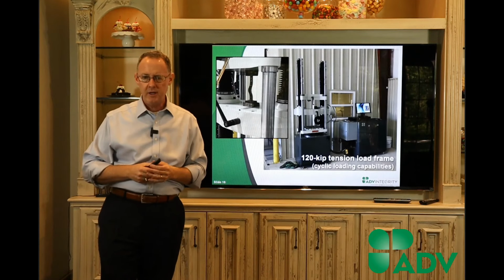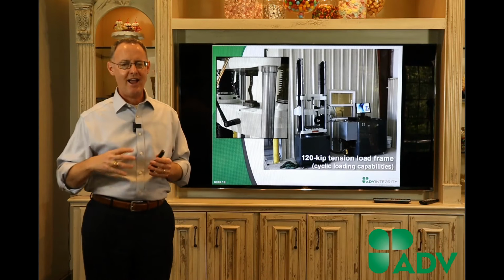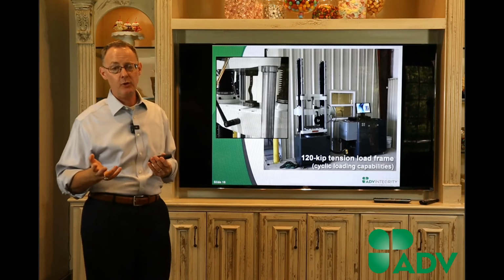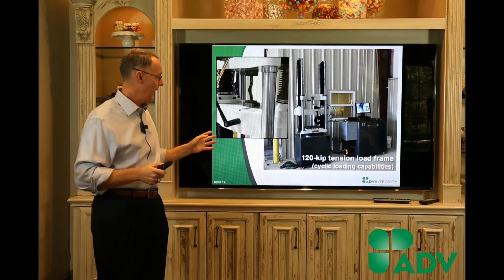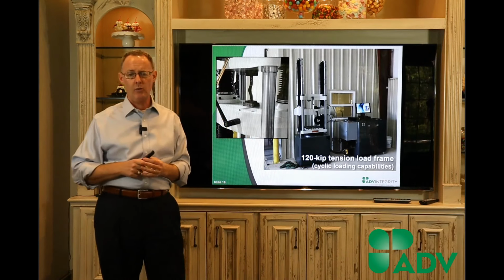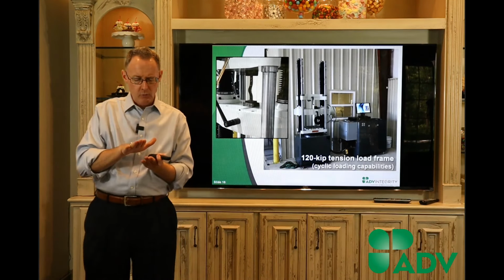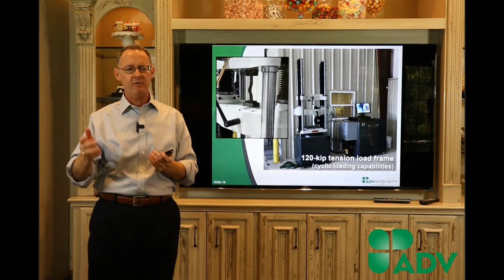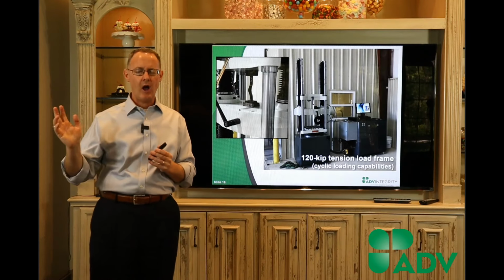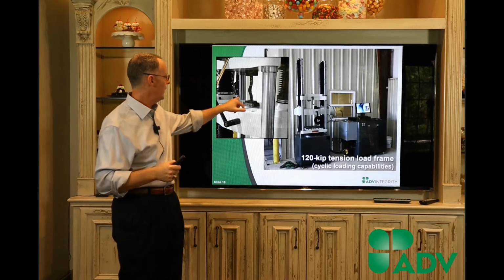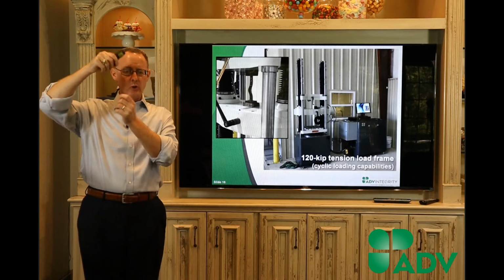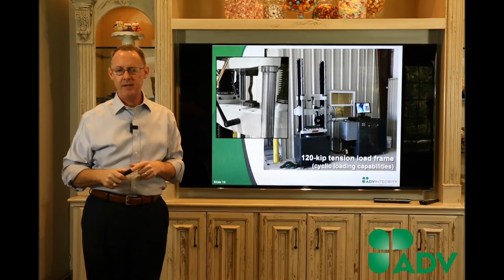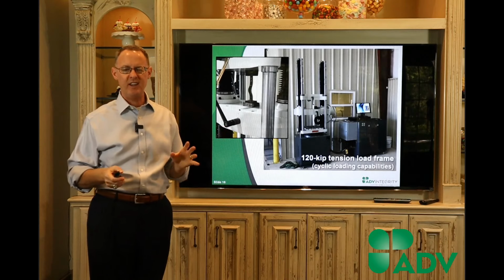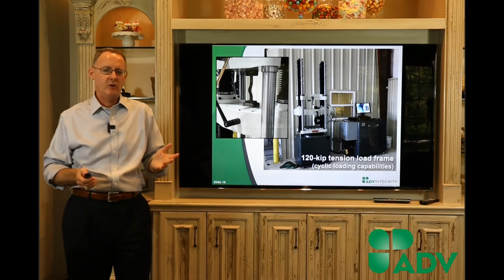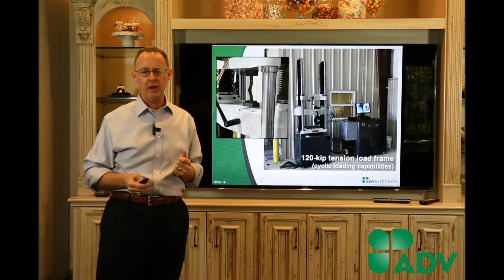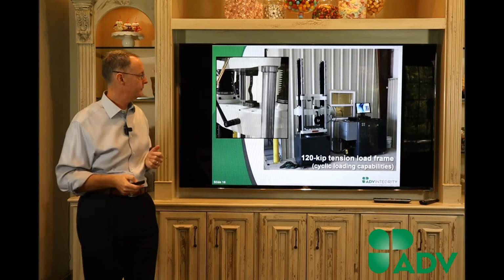So one of the other things that we did, and I will admit when we started in 2019, I did not think that we would do this, but we bought a little Tinius Olsen machine. It'll do about 120,000 pounds. It will do cyclic loading. One of the things I want to do this year is we're doing some composite work with a company, to do some fatigue testing on composite materials. It's relatively automated, but we can also do tensile samples. This is actually a wrinkle bend where we're doing some high strain, low cycle wrinkle bend testing that has worked out really well. That's just an example of the kind of things that we can do. The nice thing is if we need to do a quick pull test, we've got the facility to do something like that, and we don't have to wait to send it out.